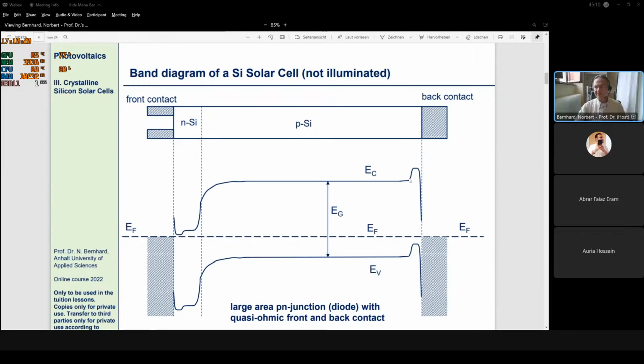And this back surface field is generated by aluminium, which is diffusing in from the backside. Aluminium is a group 3 element, and therefore is a dopant, as boron is. And that means the aluminium, which is diffusing in from the backside, is enhancing the doping here at the backside and creating this so-called back surface field, which keeps away the electrons from the wrong contact and supports the collection of the holes.